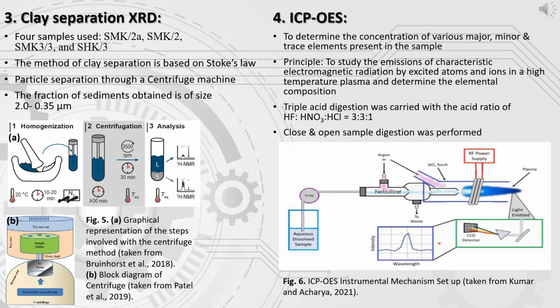The reagents used were hydrofluoric acid, nitric acid and hydrochloric acid. JB1B, basalt, obtained from the Geological Survey of Japan, was used as a standard in the test. 100 mg of the 11 powdered samples, a duplicate, a blank and the standard were measured using the weight balance machine and put into the PTFE vials, along with 3 ml of milliQ water, followed by 3 ml of hydrofluoric acid, 3 ml of nitric acid, and lastly, 1 ml of hydrochloric acid were added to the above sample in the PTFE vials. This is regarded as triple acid digestion.